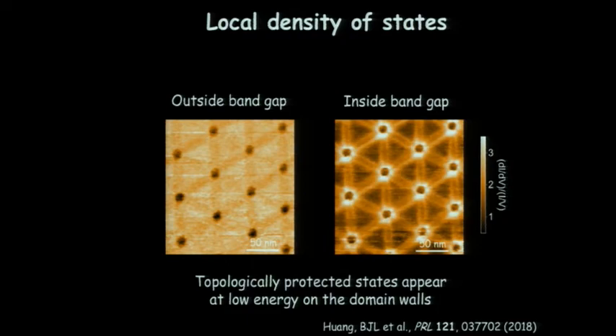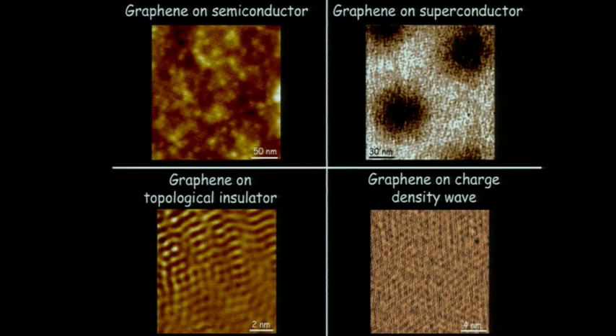Today I told you about graphene on graphene and graphene on boron nitride, but we've also looked at putting graphene on a semiconductor. This is tungsten selenide. Here's graphene on a superconductor, niobium diselenide. And then we put on a small magnetic field, and these are the vortices which show up in the niobium diselenide. Graphene on bismuth selenide. So other things.